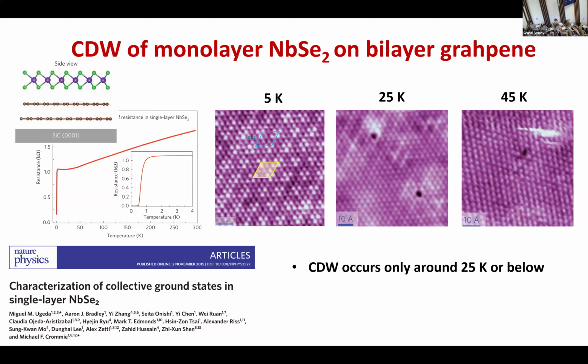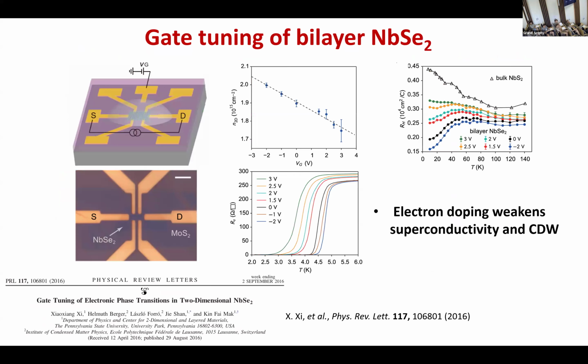In the experiment with the ionic liquid, since niobium diselenide is so sensitive to chemistry, can you really? Yes, exactly. So this is also one thing. At that time, everybody was claiming that this is a purely electrical effect. And after so many years, people are already aware that there could be intercalation and chemical effects. So at that time, in their paper, they claim they protect the niobium diselenide with molybdenum disulfide, to reduce or eliminate the chemical effect.